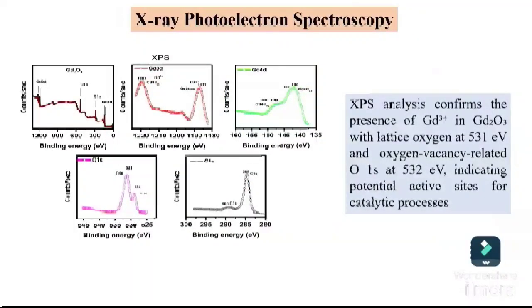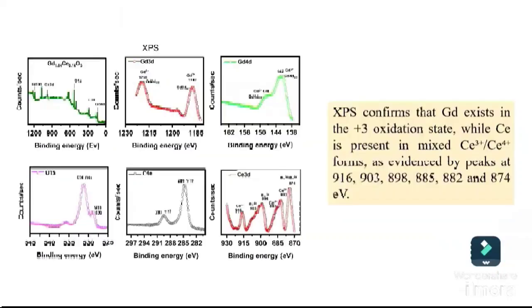This is the data for X-ray photoelectron spectroscopy, which confirms that the gadolinium has a +3 oxidation state at 531 electron volts, and the oxygen peak is at 532 electron volts. This is the slide for cerium doped gadolinium oxide, which confirms that our cerium has a mixed oxidation state, +3 and +4, and the peaks are shown at different electron volts from 874 electron volts to 916 electron volts.